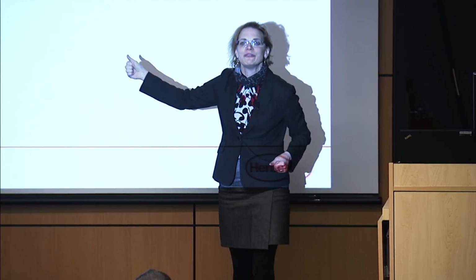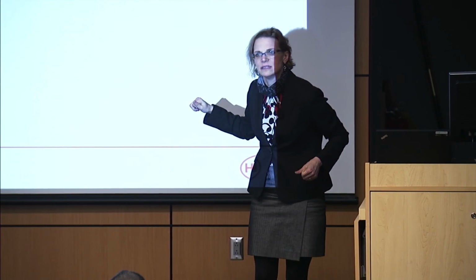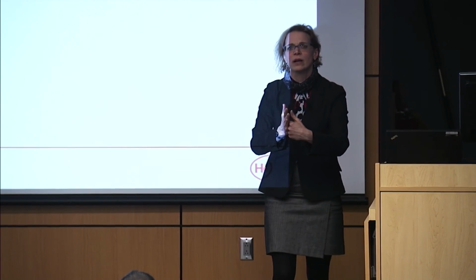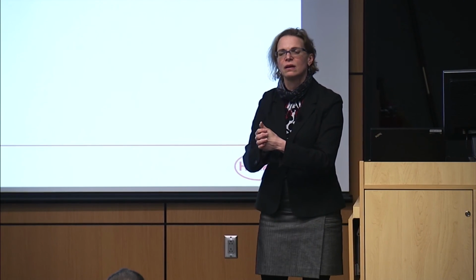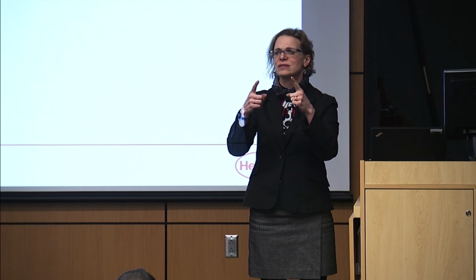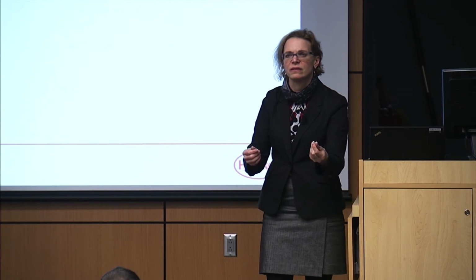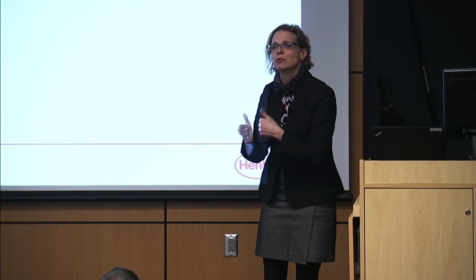So we started to say, well, how do we get that kind of energy? We know we can get a lot of heat in, but maybe your system doesn't have a lot of heat, and it still works. And a research group in Poland caught the idea that perhaps when our chart applied and you started to really hit those asperities, just about the time we discovered that you could get physical emission of electrons. And they said, well, is that possible in a frictive contact? And when you consider that on a metal surface, a metal oxide surface, you have nanometer level asperities in some cases. When those are hitting, those are very, very high pressure contacts. And it was very quickly realized that, oh yes, you can throw a lot of electrons from those surfaces.